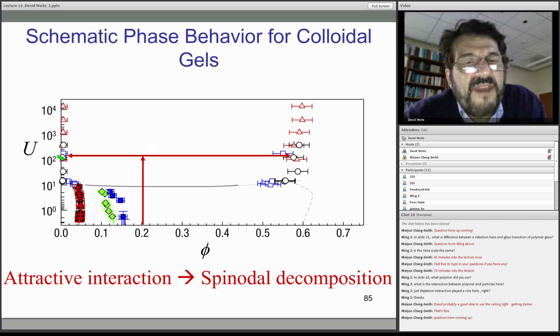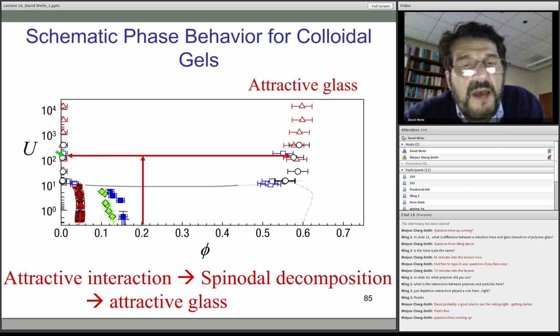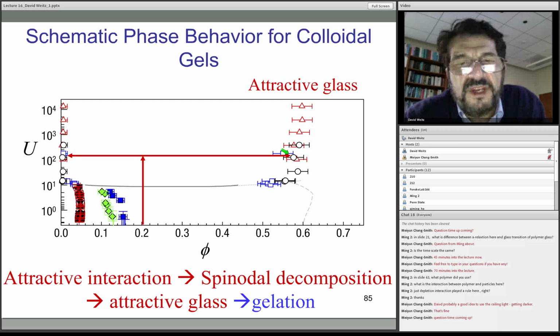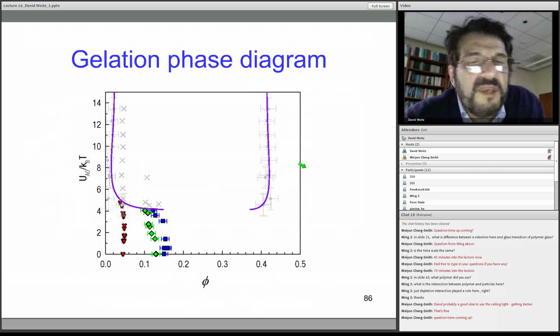You're getting spinodal decomposition into this gel structure and to the structure where there's no particles. And this region here is freezing because you're going into a colloidal glass region. And it's freezing. It's becoming a frozen region of a spinodal decomposition, an interconnected network of a colloidal glass. So this is a very simple physical picture of why you get gelation.